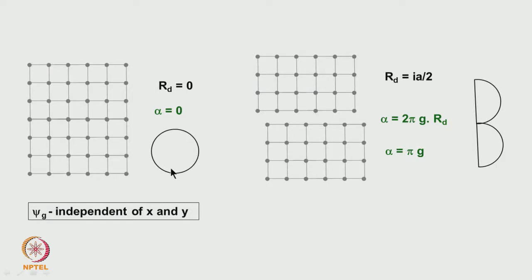So even though there is a defect, okay, depending upon the g vector which you use, that is specifically dependent upon the fault vector, that decides for some g vector you find that in this particular case the amplitude can become reversal of it. In the other case the amplitude becomes normal.